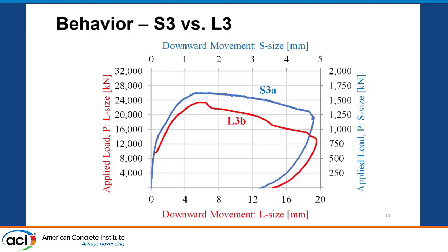Another observation here is they crack at approximately similar times, but that the post-cracking stiffness of the largest specimen is actually smaller than the post-cracking stiffness of the smaller specimen, sort of a tension stiffening result there. So that was an interesting observation there.